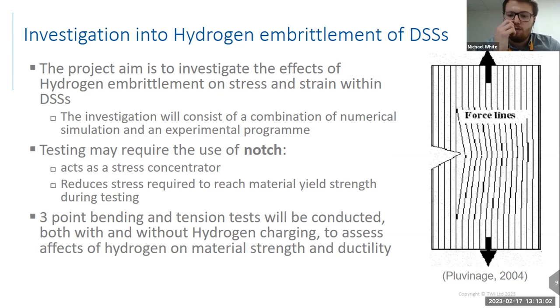A combination of numerical simulations and experiments will be conducted, starting with a three-point bending test with a notch integrated. Notches are noted as a stress concentrator, which will allow us to assess the point of initiation of crack forming by limiting the area at which a crack could occur.